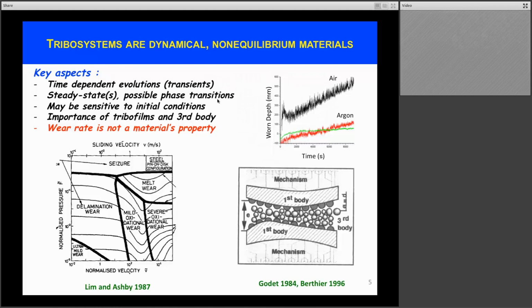However, it is well documented that if we vary the conditions under which we perform the test, this steady state wear rate may change. In fact, Ashby and his co-workers, for instance, developed this concept of wear maps, where here we see different regimes for wear of steel on steel, and as you cross these thick line boundaries, you may go from one type of wear to another. These boundaries are not always known ahead of time, and so it is difficult and challenging to design wear-resistant materials because by changing operating conditions, you may change the operating point of the material from one field, one domain, to another.